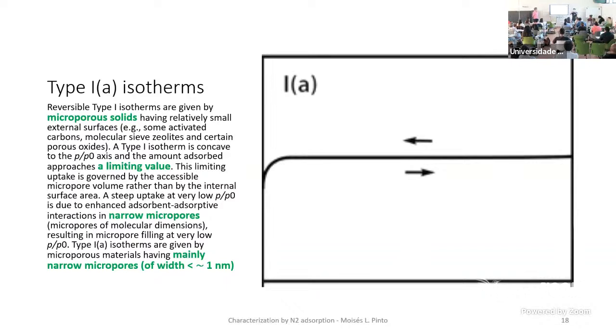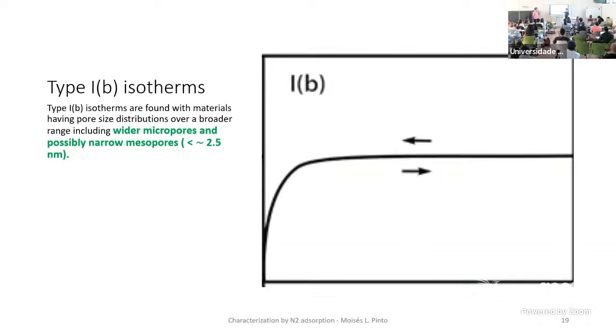When we take an isotherm of a material, just from looking at the shape, we already know quite a lot of things. One is, for instance, if it is like this, what it means is that most of the adsorption occurs at very low pressures. So it means that the adsorption potential is very high. It means what? That you have very narrow pores. Yes? So this is typical of microporous materials. Yes? So sometimes the curvature is a little bit more open. What it means is, okay, the pores are probably already a little bit larger. Yes? Nevertheless, sometimes we already start to have some narrow mesopores around this value, if it is like this. Yes? And you see in here, if this is completely reversible, this is physical adsorption. Yes? So you can have some desorption points to see if this is reversible.